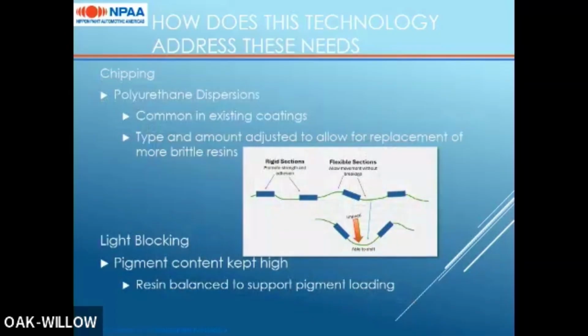Additionally, these coatings are designed with a higher level of polyurethane dispersion. Again, this is pretty common in most existing coatings, but it has been optimized for this, and the type and amount are used as a replacement for more brittle resins that are typically used in a base coat, such as acrylics.